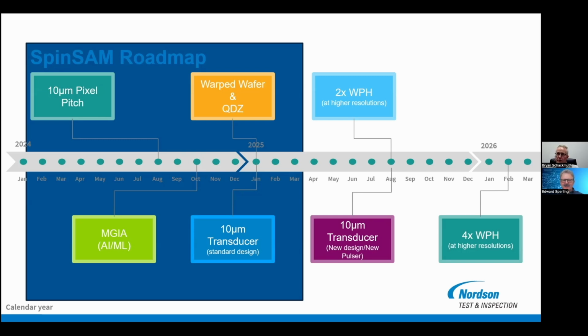Correct. And one of the things, right now the wafer chuck we are currently using will take the warpage out of the wafer. So if there's a few hundred microns of warpage, we apply a vacuum and it basically flattens the wafer. Some customers are okay with flattening the wafer if it's a minor amount of warpage. When you get into that 3 millimeter range, you don't want to flatten the wafer with suction because you might induce stress on it. So we're moving to a 3-pin type wafer chuck. The warpage stays in the wafer and we optimize on that based on the QDZ or that dynamic focus. This all feeds into where you actually singulate the individual die in the wafer.